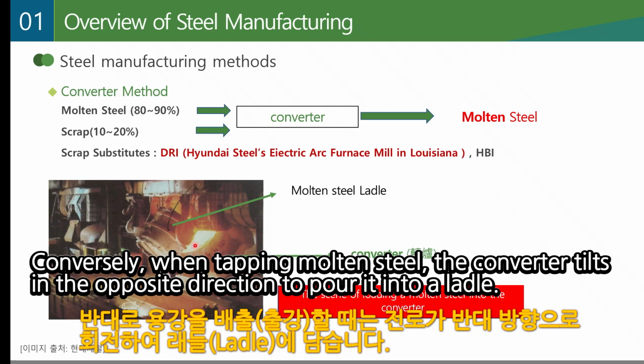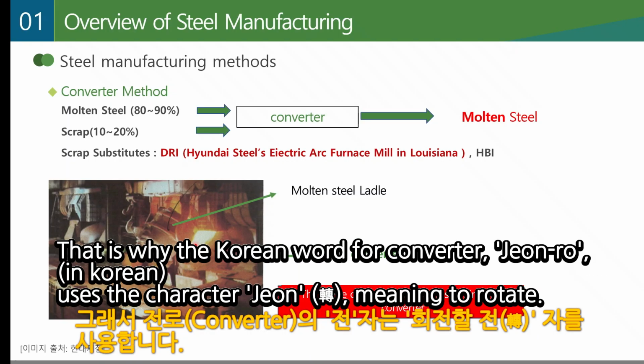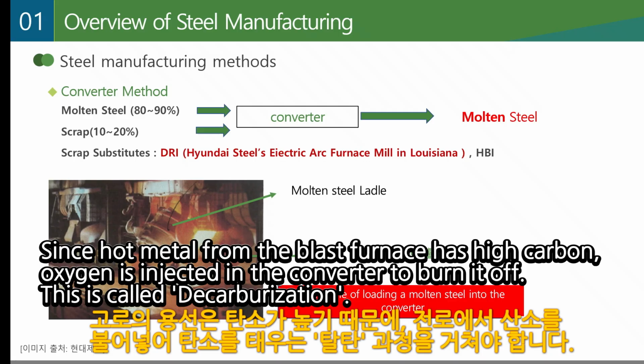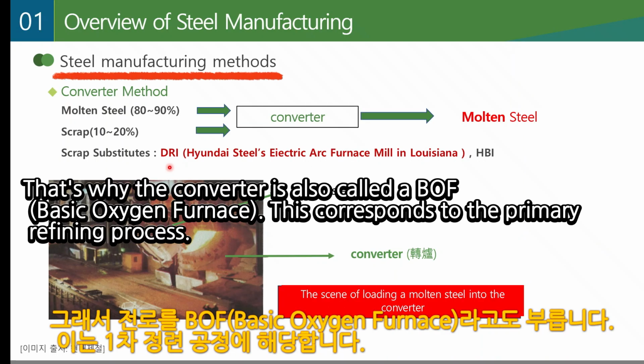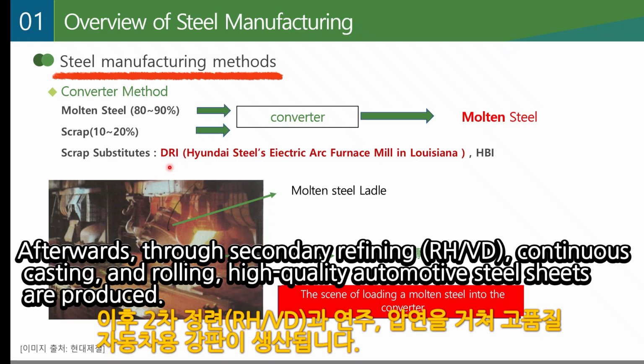Conversely, when tapping molten steel, the converter tilts in the opposite direction to pour it into a ladle. That is why the Korean word for converter, Jeon-ro, uses the character Jeon, meaning to rotate. Since hot metal from the blast furnace has high carbon, oxygen is injected in the converter to burn it off. This is called decarburization. That's why the converter is also called BOF, basic oxygen furnace. This corresponds to the primary refining process. Afterwards, through secondary refining, RH/VD, continuous casting and rolling, high-quality automotive steel sheets are produced.